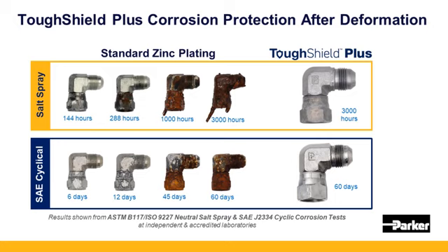And then finally, Toughshield Plus really delivers significant corrosion protection after a product's been deformed, plated, and then deformed during processing. So that's a significant limitation of any traditional zinc fitting, as well as most zinc-nickel platings. So for components like these, where our industry relies on these swivel nuts, backup washers, staked products, and even the sharp corners and threads,